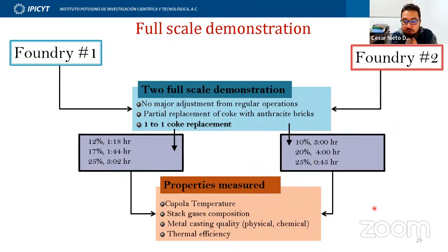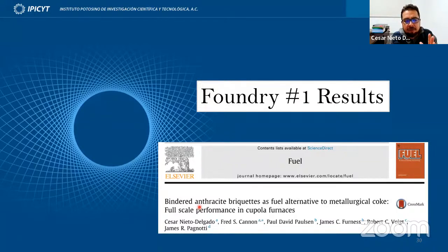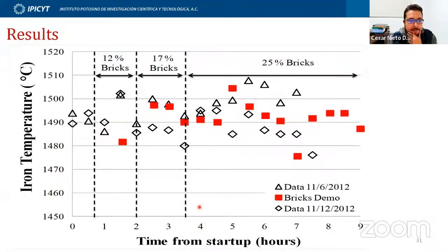We measured a lot of things, but mainly we measured the cupola furnace temperature, which is one of the main concerns when you put anthracite in a cupola furnace. We measured stack gas composition, metal casting quality, and also thermal efficiency. Now, most of this information that I am about to show you is in this paper. In this plot, I am showing you the iron temperature versus the time from the startup.